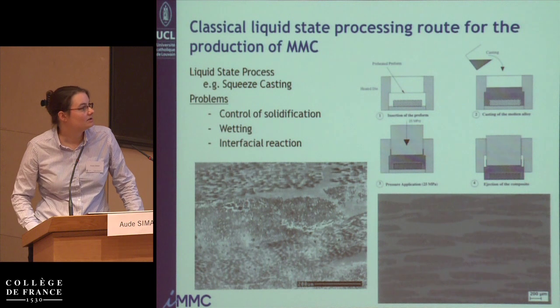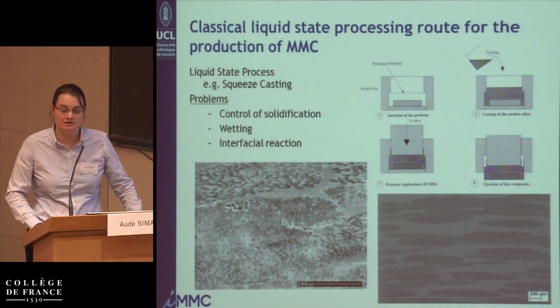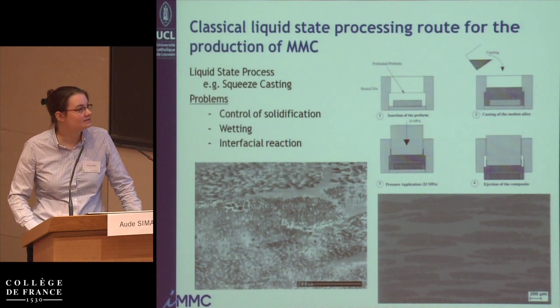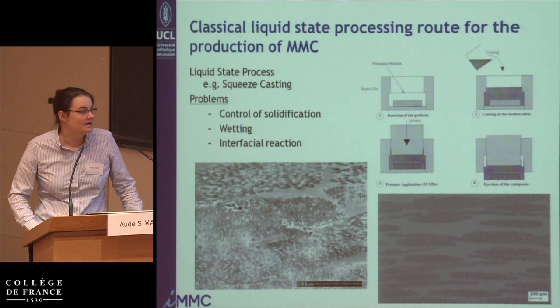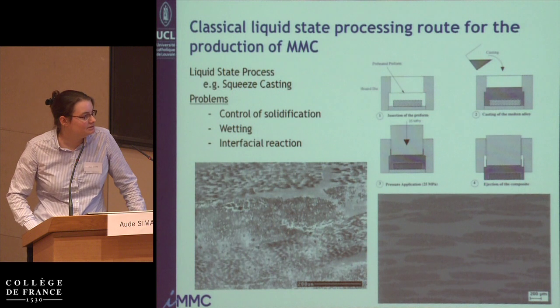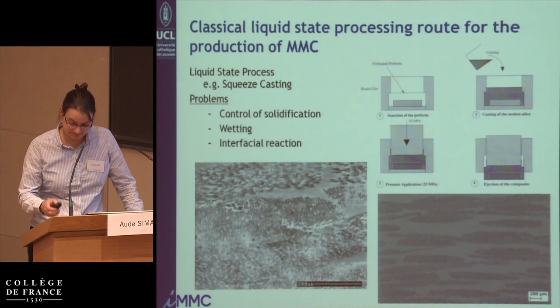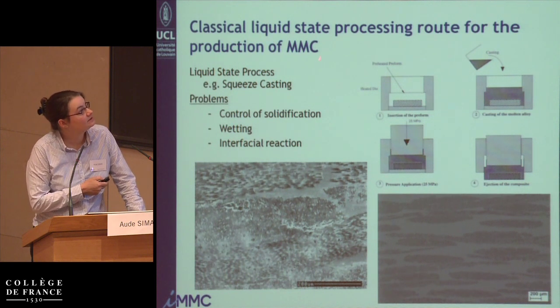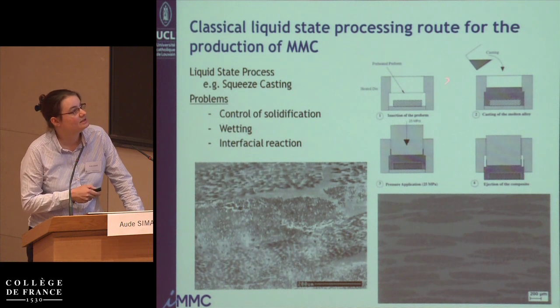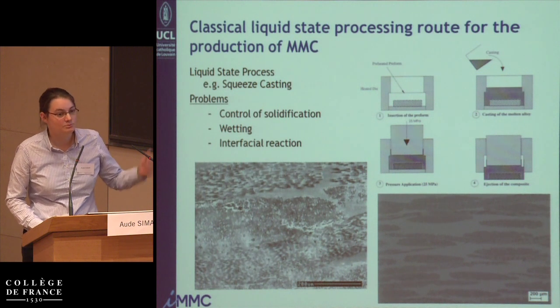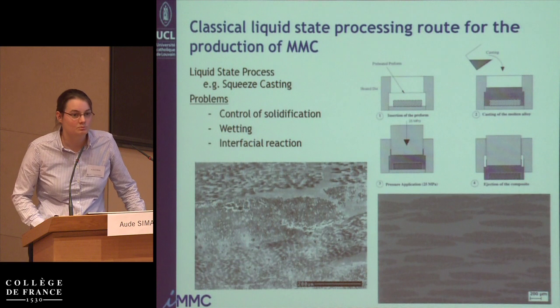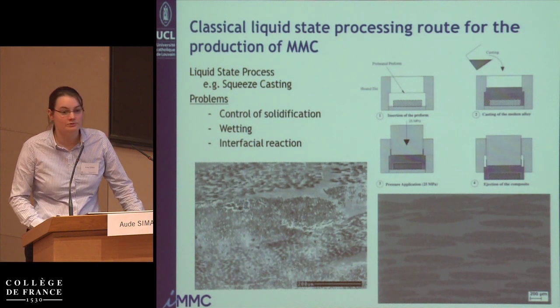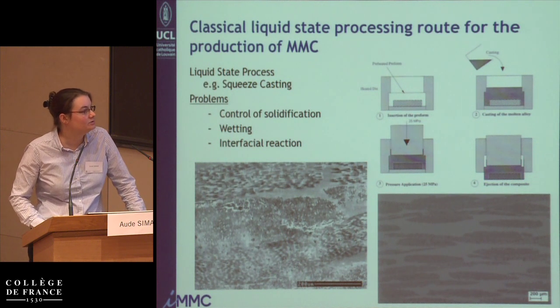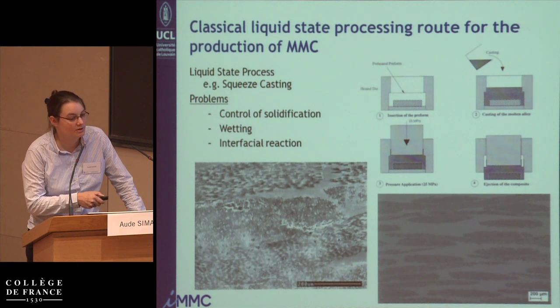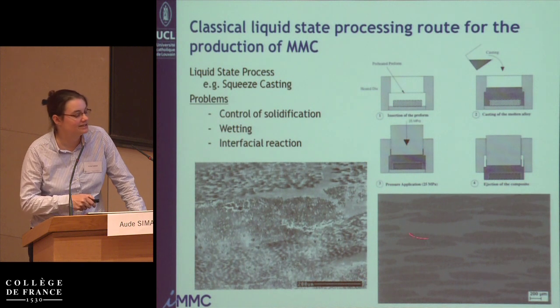The problem of making metal-based composite materials is that you need a processing method for putting the reinforcement in contact with the metal. Classically, you do that by some liquid state processing, for example, by squeeze casting. Here you put some preform, you put some liquid metal inside and you apply pressure, and with this pressure you infiltrate the preform and produce things that look like this. So you have here a composite of carbon fiber and a magnesium matrix.